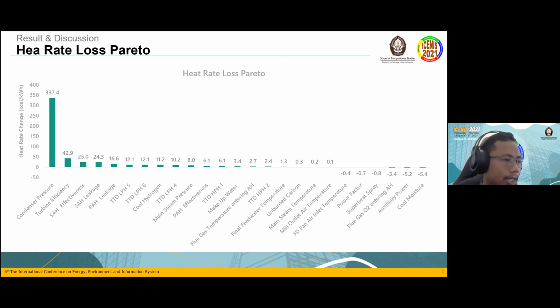The result of the heat rate deficiency analysis is that the most significant increase in heat rate was due to condenser pressure increasing by 9.9 kilopascal. Possible causes of the condenser pressure increase are air in-leakage, excess condenser load, tube fouling, low circulating water flow, tube plugging, air binding, and increased cooling water inlet temperature. The second significant cause is the turbine isentropic efficiency decreasing by 2.3%. Possible causes of the decrease in turbine isentropic efficiency are mechanical damage, mechanical blockage, blade deposits, spill strip, turbine stick erosion, gland seal leakage, and main stop valve leakage.